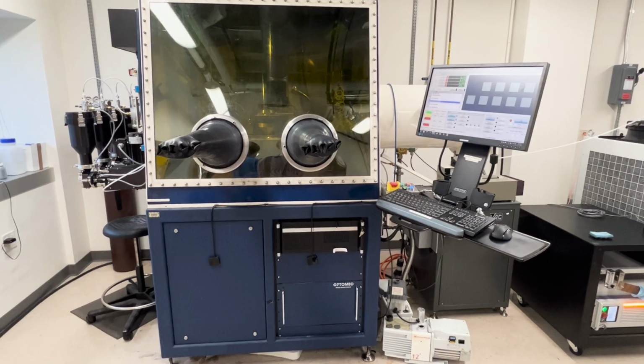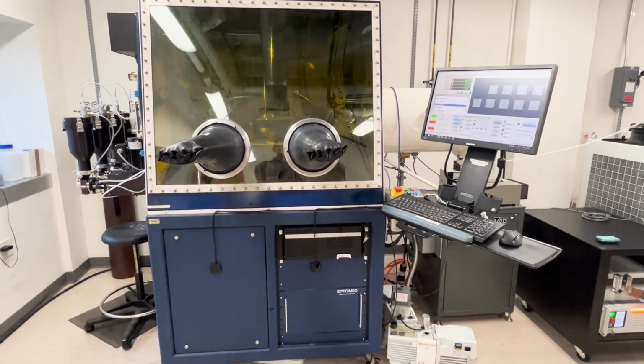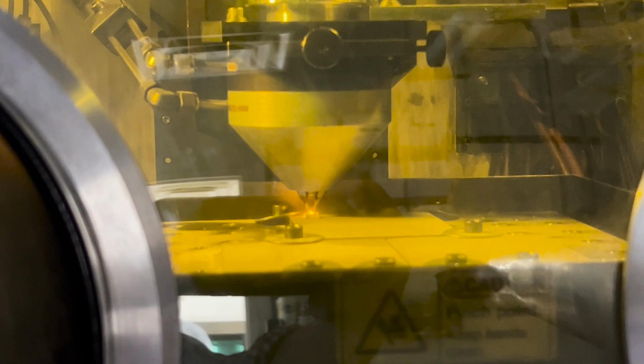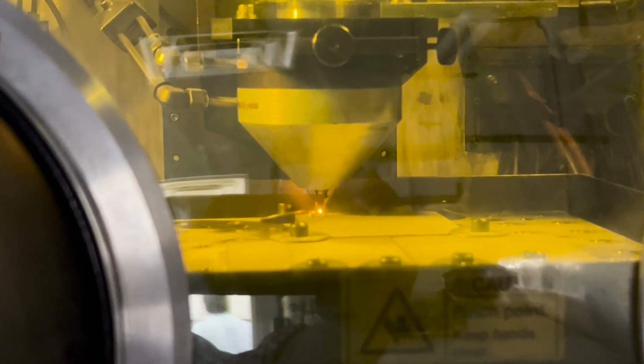We have some advantages through the laboratories here at UW-Madison with our additive manufacturing. The additive manufacturing technologies allow us to make a variety of samples and do compositions on the fly. We also have good arc melting capabilities where we can look at these refractory materials. Refractory means typically they're going to melt over 2000 degrees C.